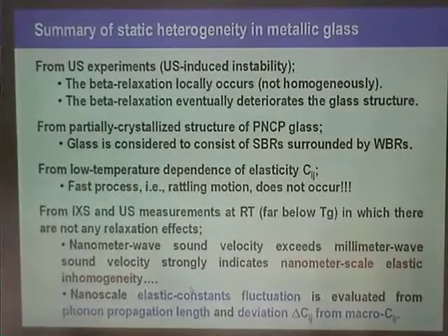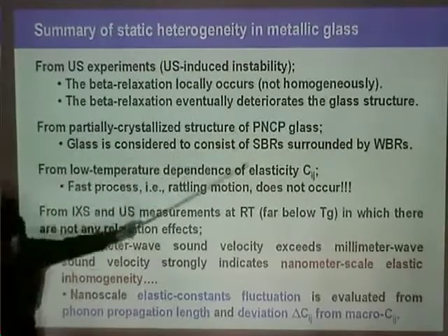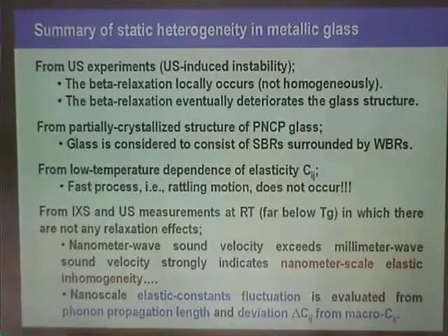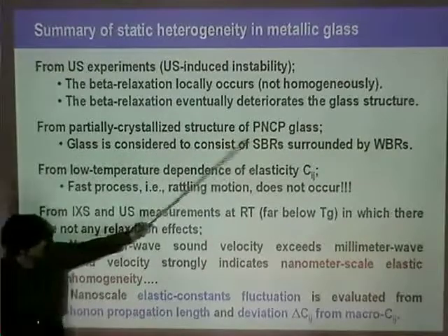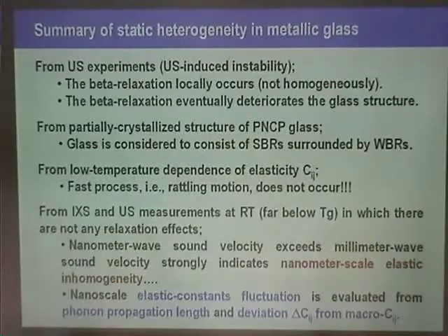Okay, so a summary of the static heterogeneity. From our ultrasonic experiments, the beta relaxation occurs locally, not homogeneously. The beta relaxation eventually deteriorated the glass structure. And from the partially crystallized structure of palladium, nickel, copper, phosphorus metallic glass, the glass is considered to consist of SBR and WBR.